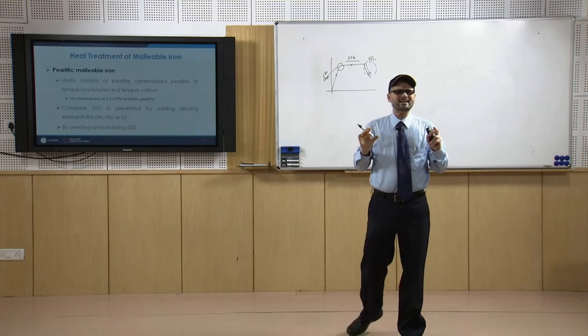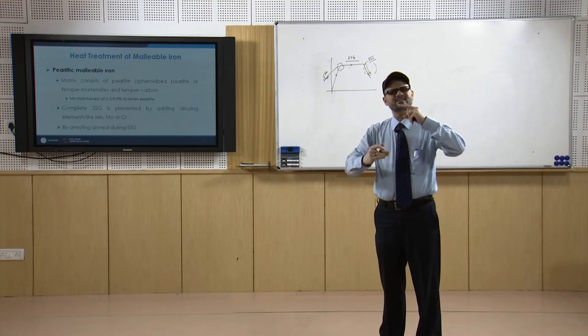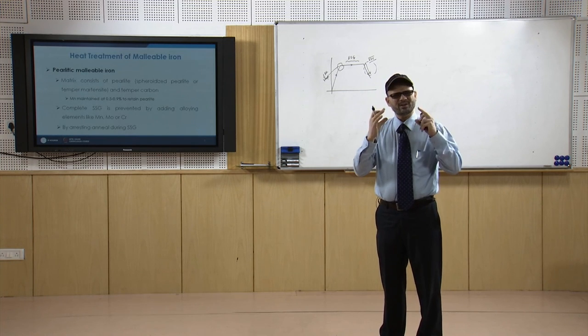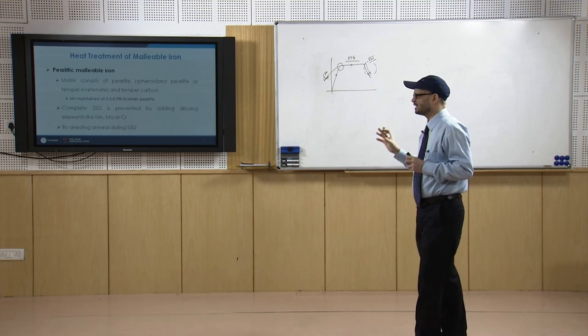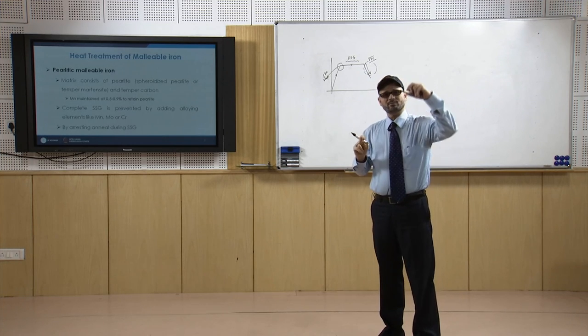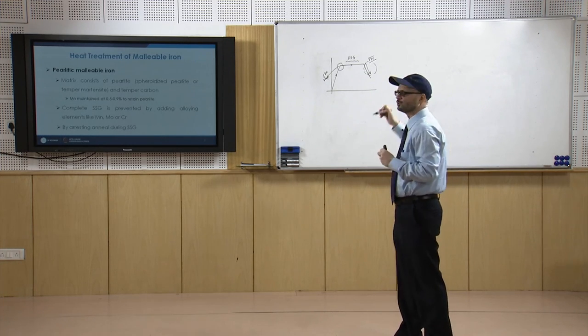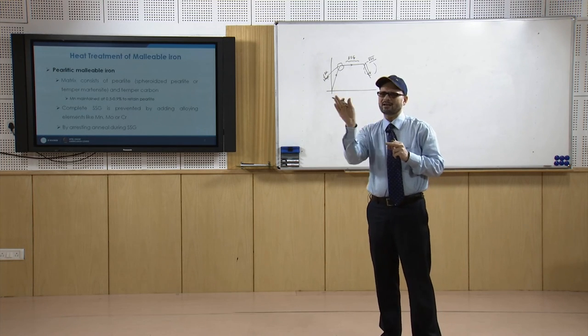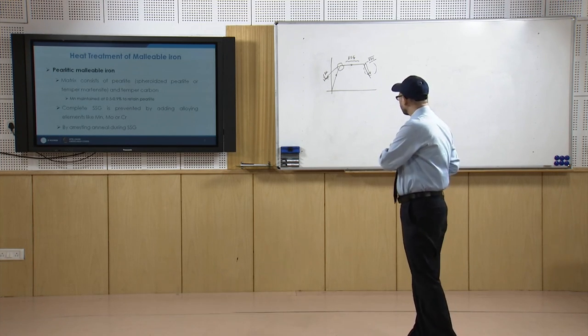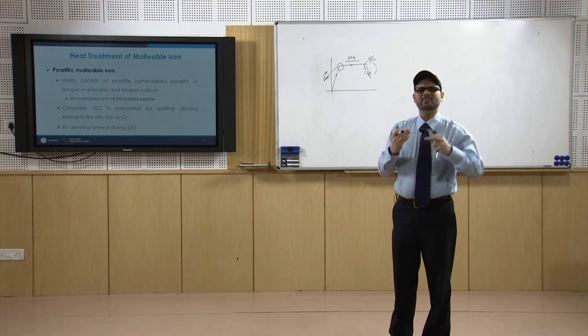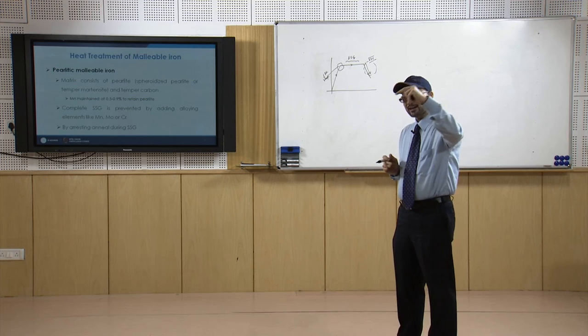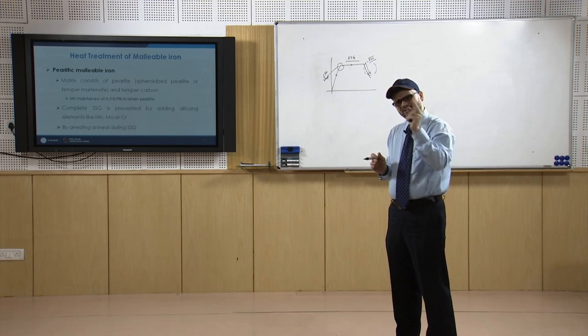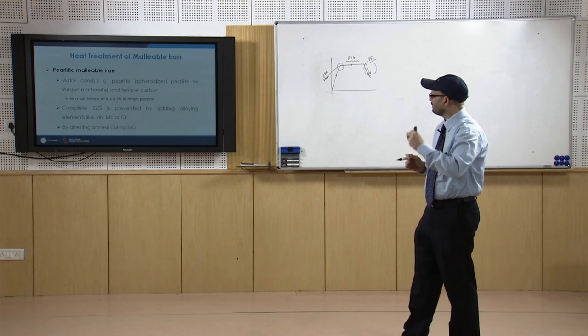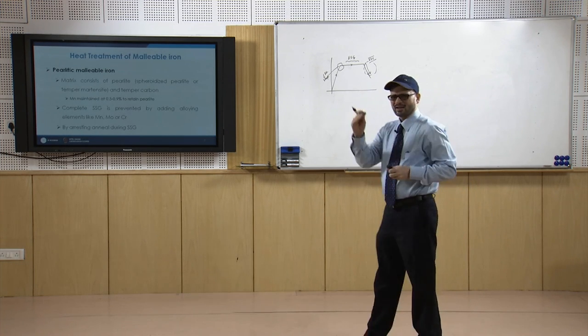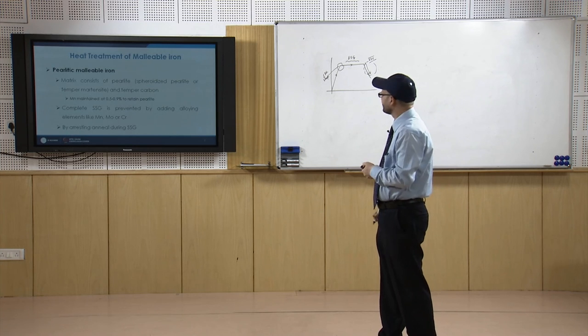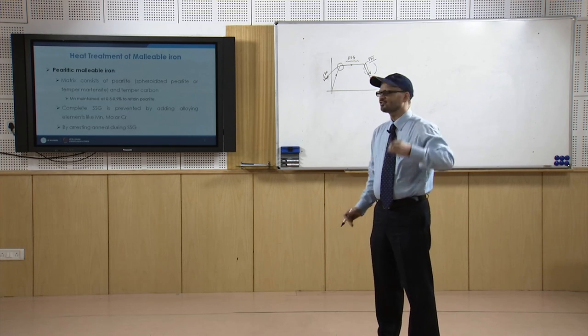During the second stage graphitization, the result of SSG is the formation of ferritic structure. Now that is to be prevented, and if the cooling rate is fast in these cases, if you further heat and then cool fast, you get the pearlitic matrix. So if the cooling rate is slow, the ferritic matrix is obtained. However, if this SSG is prevented, you get the pearlitic matrix. So that gives you more strength.